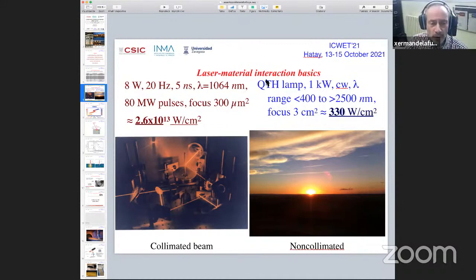You can focus a 1 kilowatt lamp, for example, a quartz tungsten halogen lamp, which emits in a continuous mode and in a range of wavelengths, which goes from almost the UV to the near IR, with a great effort into a 3 centimeter square area. This gives you, if you calculate it for the 1 kilowatt, a power density of 330 watts per square centimeter, from a radiance, which is the power density basically.